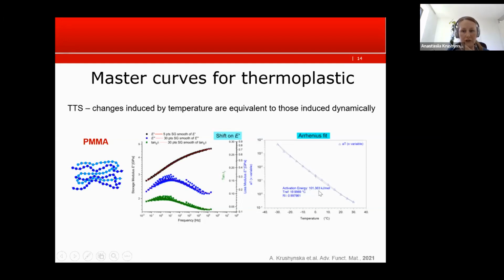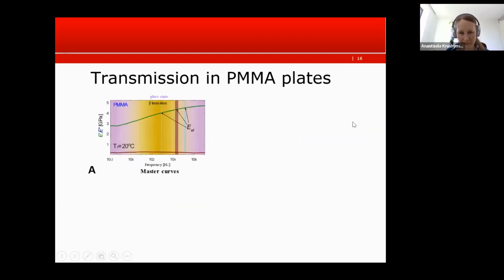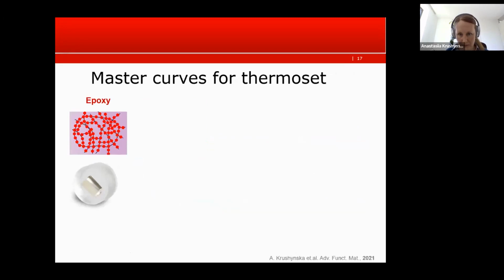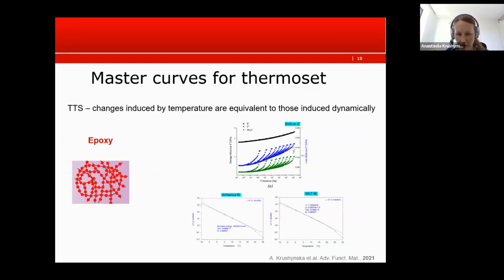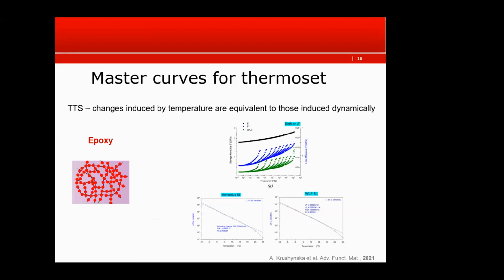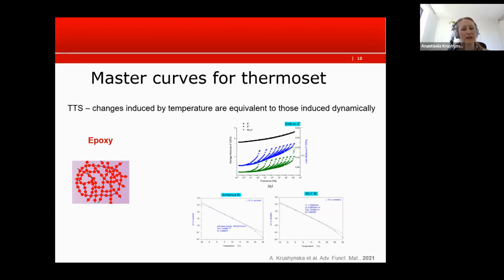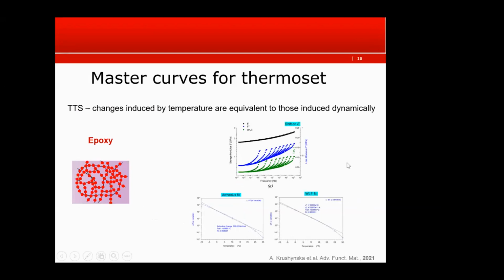And the activation energy value should be meaningful. This is exactly the reason why for the epoxy case, so let me open it. Here, the activation energy was not meaningful. Even the fit was not that bad, okay, except some deviations, but the activation energy did not correspond to the one reported experimentally. So that was the quality of a bad fit, in addition to not nicely looking curves.